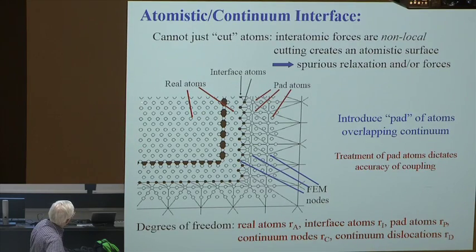I'll have this body with the forces applied. But in fact, these atoms in here are missing atoms that used to exist over here. And so these atoms should also have forces on them if I wanted to really reproduce exactly this structure. That is, there's a kind of a domain over which the system is non-local. I can't just cut and apply forces.